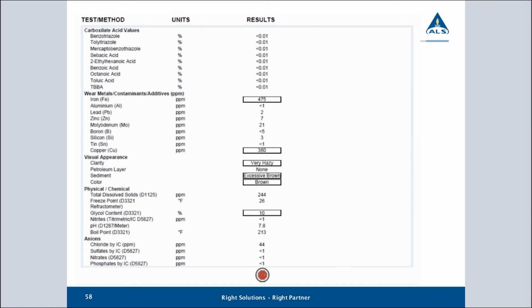So again, the reaction we need here is very much depending on the current health of the system. Generally, a system in this condition is not going to be in good health. We need to establish the health of the system. We would need to remove this coolant as quickly as possible and replace it with something that is better suited to working in a cooling system. But normally when I see results like this, you're probably looking at a system that's due for a rebuild because it has been pushed too far.